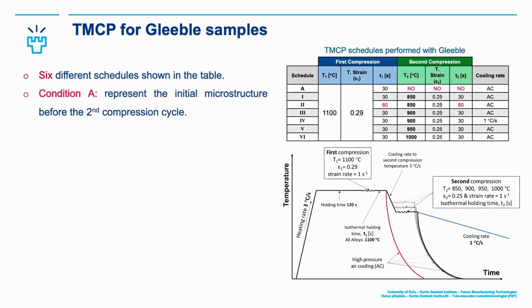Moving to the TMCP samples. As I mentioned, there are 6 schedules, so you can find them here. Schedule A we can forget for now. We have schedules from 1 to 6, and the schedules are done in 2-hit compression, first and second compression. The first compression for all of the schedules is at 1100 degrees, and the true strain is 0.29. The first schedule, named A, was used as a reference, so we don't have a second compression here, it's just the first. This is the result from the first compression. The temperatures here are 850, 900, 950, and 1000.